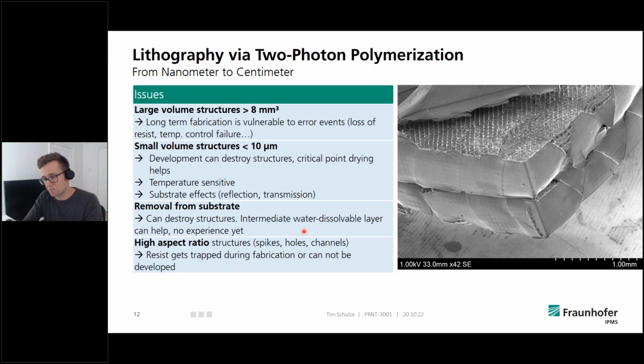And also the summers were really hot in Germany and in the lab. If you're not able to control the temperature, this could also lead to some little deformations in very, very tiny structures. And this could also lead to results you are not happy about. So this really needs to be considered when printing your structures. And on the other hand, if the structures are really tall, it can also happen that during the washing of the resist, when you're done with your component and you want to get rid of the resist, structures get deformed by surface tension of the solvents.